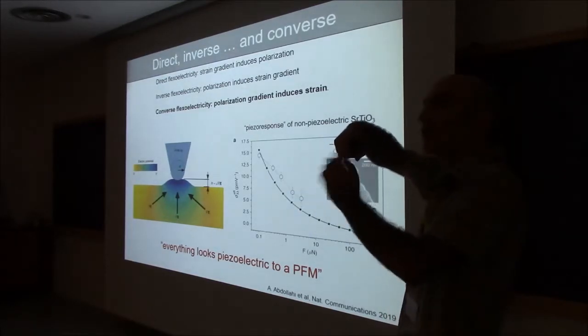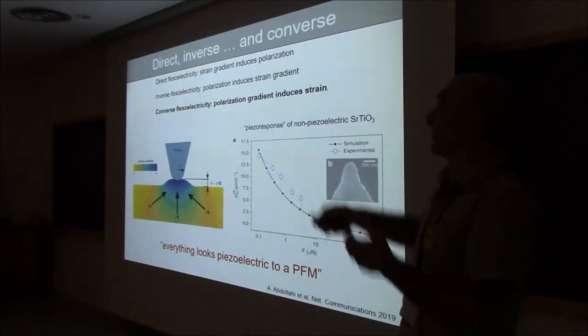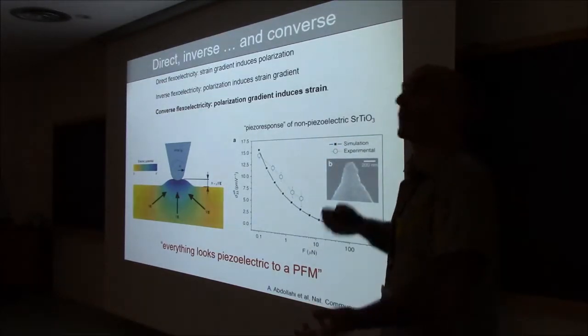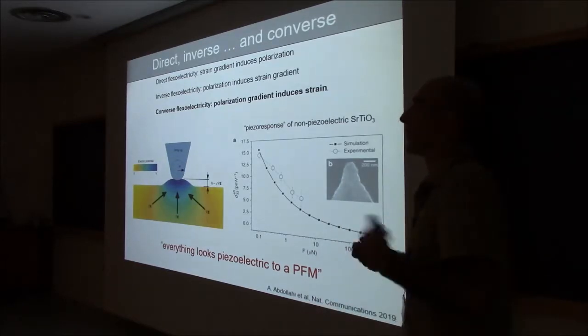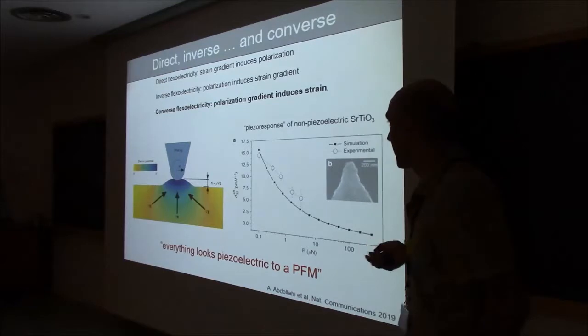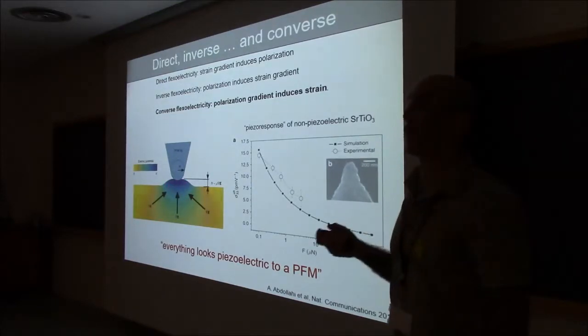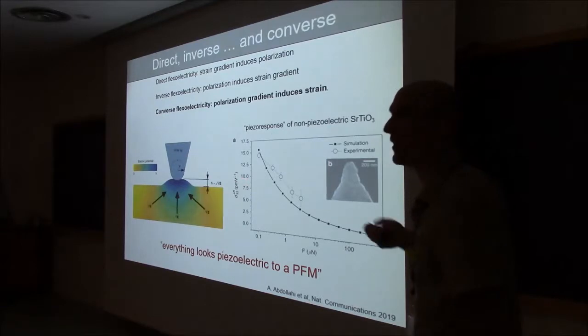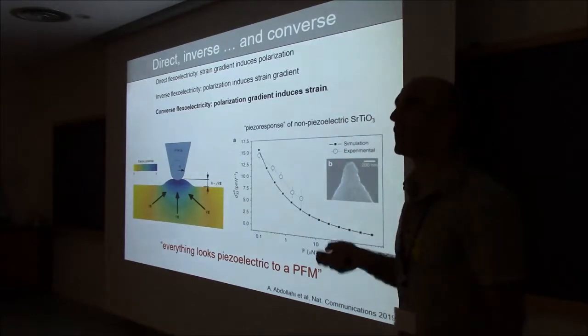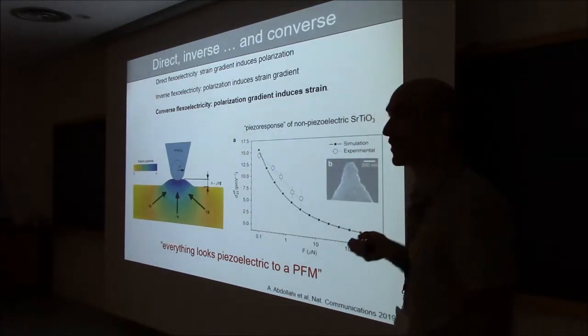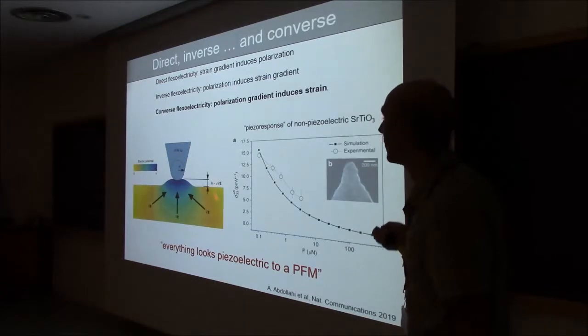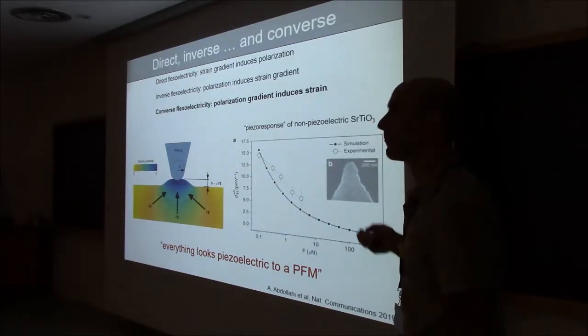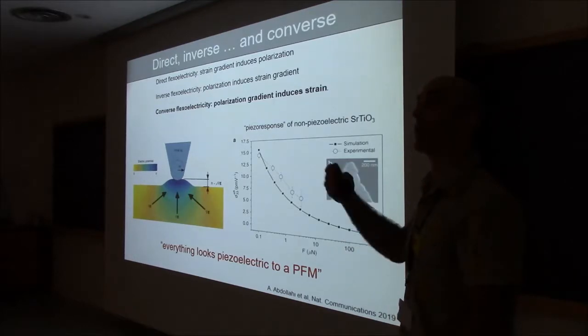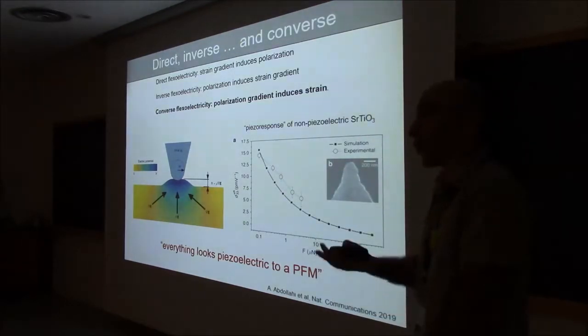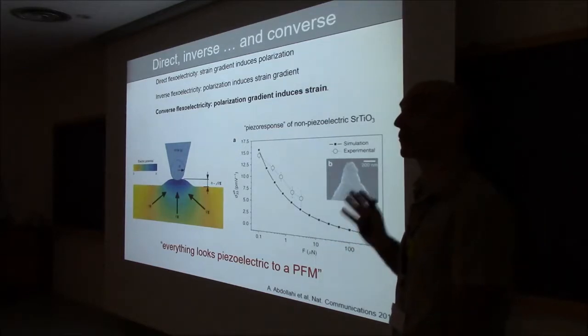So what you do is you apply a voltage to your tip. This voltage is sensed by your material, and your material will stretch or not if it's piezoelectric. And you think that if it's not piezoelectric, it's not going to deform. However, the electric field that you're applying is not homogeneous. It's kind of more or less radially decreasing as you move away from the tip. So if you have an inhomogeneous electric field, you are going to induce an inhomogeneous polarization, so a polarization gradient, and that's going to give you a strain. So when you divide this strain by the voltage that you apply to the tip, you're going to measure an effective piezoelectric coefficient, but it has nothing to do with piezoelectricity, it's pure flexoelectricity.